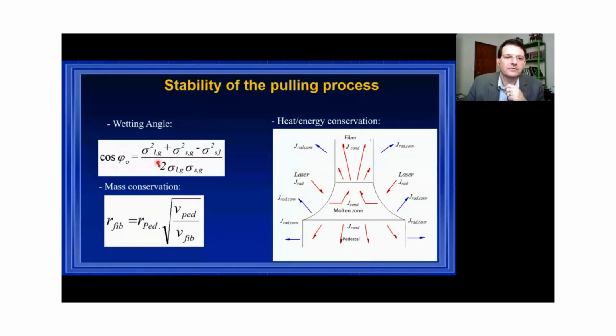So this laser technique has a threefold feature that must be satisfied, and we can extract some information from these threefold features, okay? First of all is the wetting angle. Each material has a wetting angle that will keep all the surface tensions in equilibrium, okay? So if you keep this angle constant, this is the challenge, the diameter of the crystal grown will be constant. But the pedestal is not perfect, so it fluctuates. So you need to compensate that. That's why we have a diameter control system.